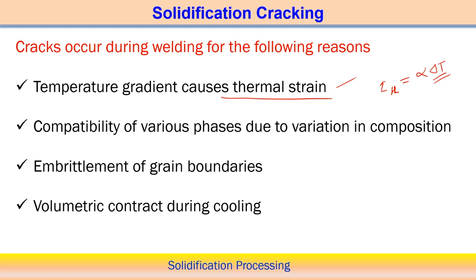Apart from this, there is the compatibility of the various phases. Different phases form, and the composition is also different for the different phases. Therefore the compatibility issue between the different phases may also influence cracking during the solidification process. Also, the presence of a low melting point component may create grain boundary embrittlement, because the low melting point material can penetrate the grain boundary and initiate a crack. That is also responsible for solidification cracking, because of the presence of low melting point material in an alloy system or during the welding process, which creates embrittlement of the grain boundary.